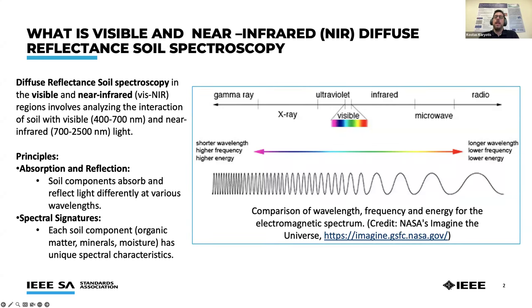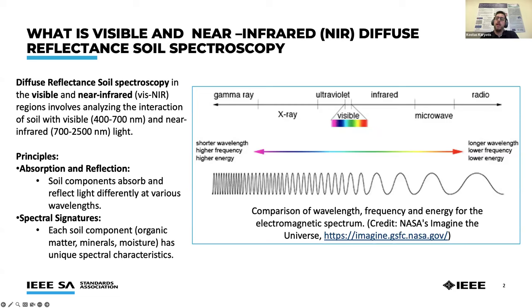Spectroscopy is a technique for delineating the chemical composition of a substance from analysis of the variation in the spectrum of light. Diffuse reflectance spectroscopy is an analytical technique used to measure the reflectance of light from a sample surface within the visible to near-infrared range. Unlike traditional spectroscopy which measures transmission through a sample, diffuse reflectance captures light scattered in many directions due to interactions with the sample's particles or surface texture. This method is particularly effective for analyzing soil, solid, or opaque materials, providing insights into chemical composition, physical properties, and structural features.